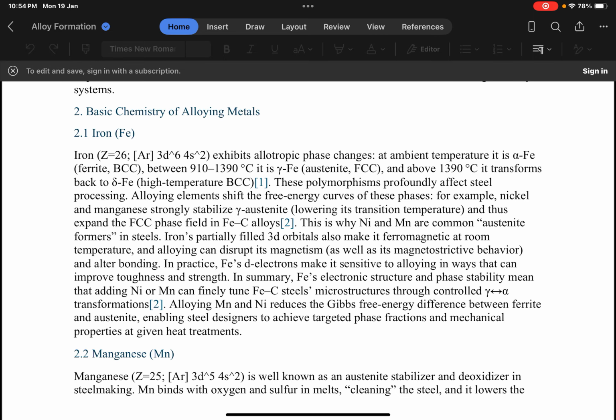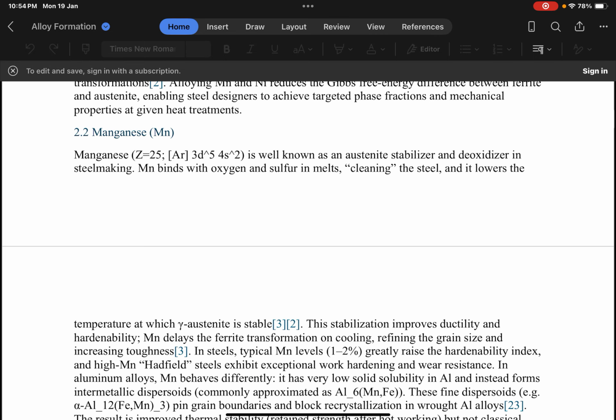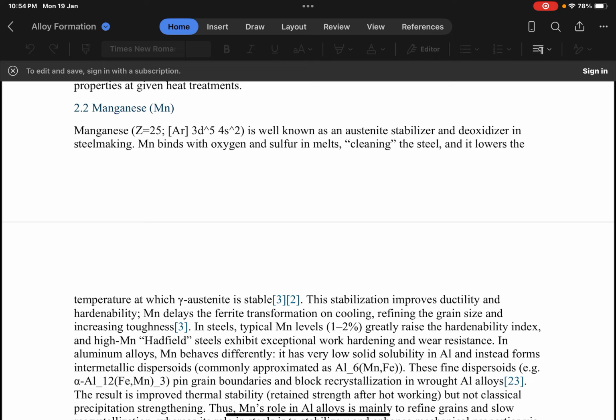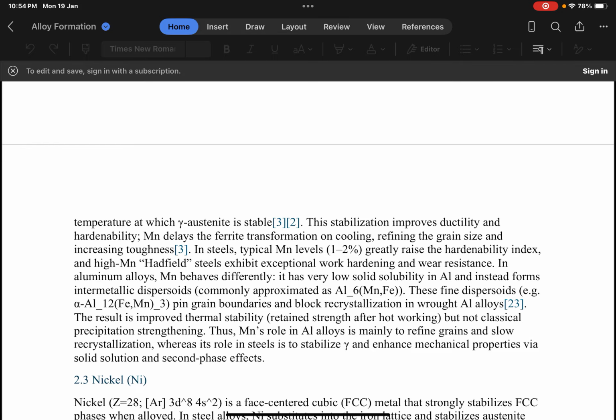Now let's talk about manganese. Manganese is widely used in steel making as an austenite stabilizer and deoxidizer. It removes oxygen and sulfur impurities and improves steel cleanliness. Manganese also delays the transformation from austenite to ferrite, allowing deeper hardening during quenching. High manganese steels such as Hadfield steel show exceptional wear resistance and work hardening.